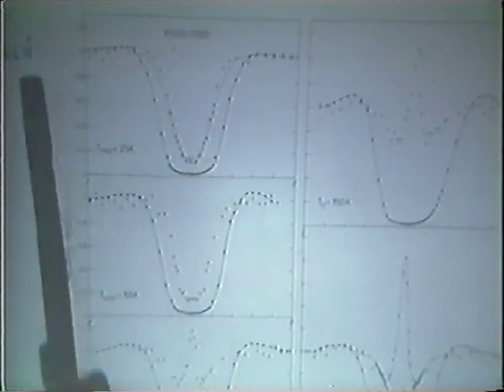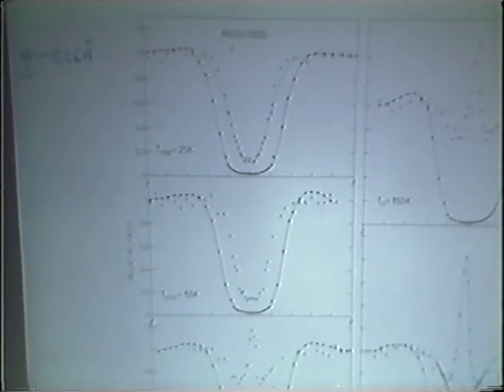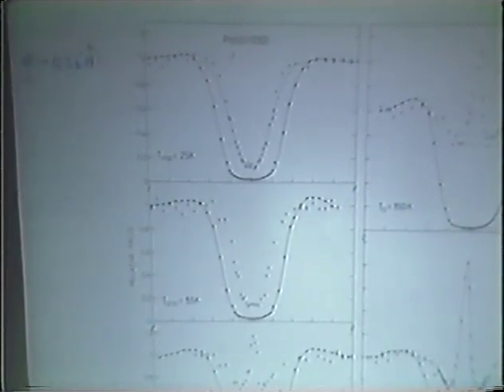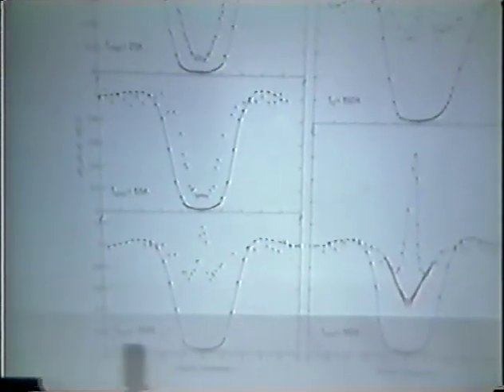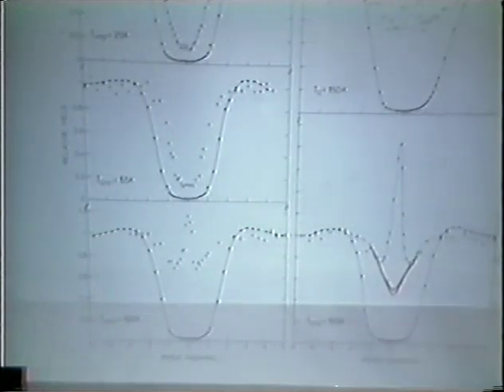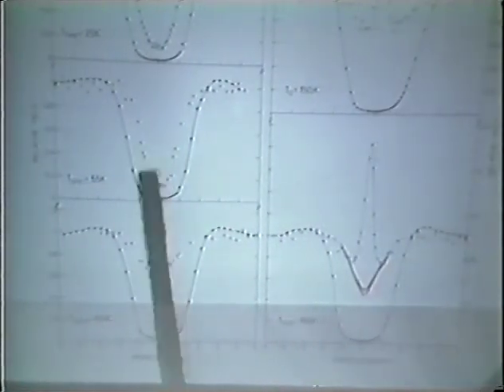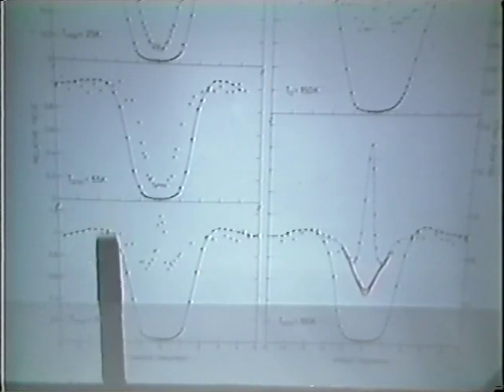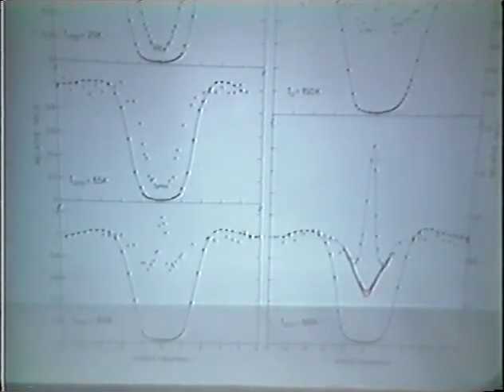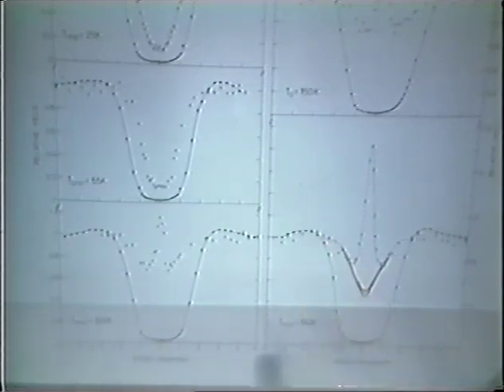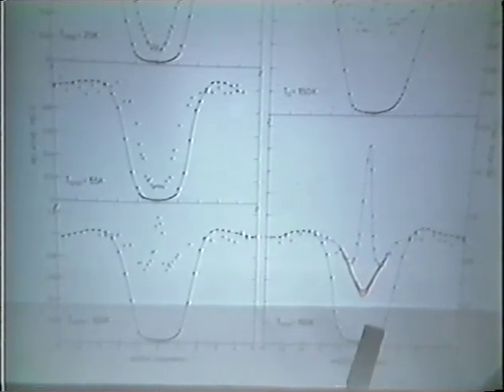I should also say that this narrowing here gives a root mean square displacement amplitude of hydrogen in a vacancy, which is 0.25 angstrom. Then you start to anneal up, with isochronal anneals of 15 minutes at a certain temperature, and you then cool down again and measure at low temperatures. And you then start to see, when you come up around 50-100 K, that the hydrogen starts to be mobile. It goes to the strongest traps, which are the vacancies. And at the highest temperature here, we have all the hydrogen associated with vacancies.